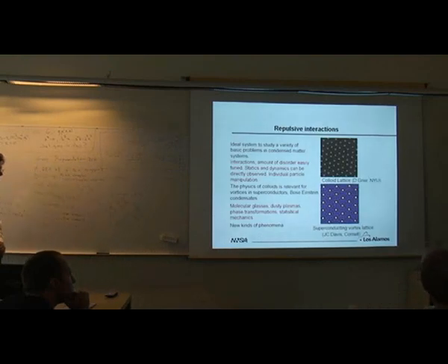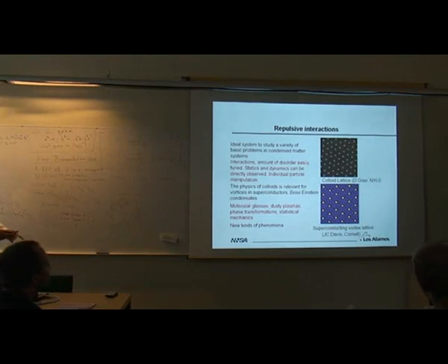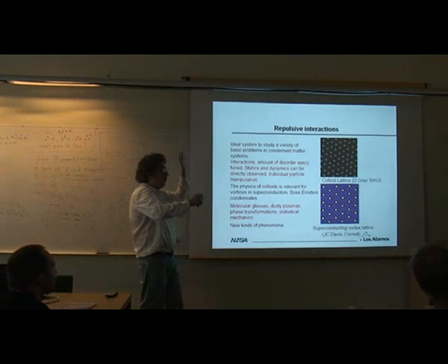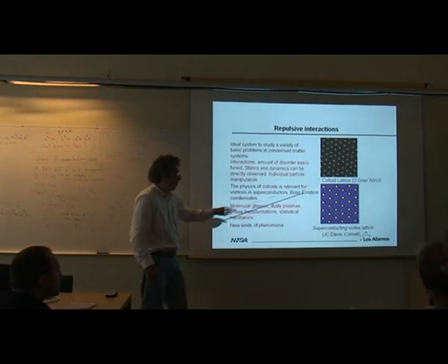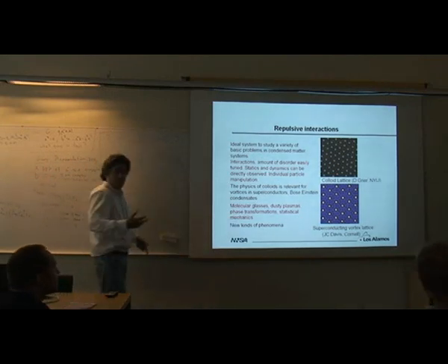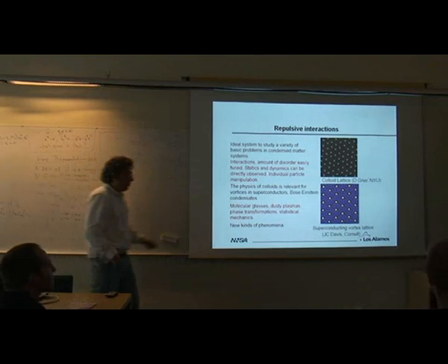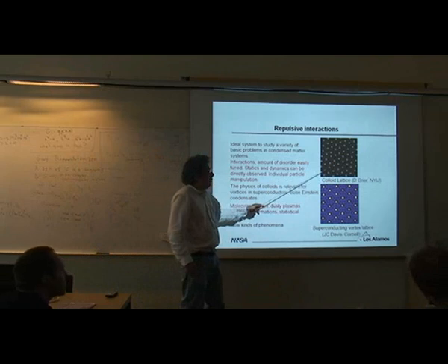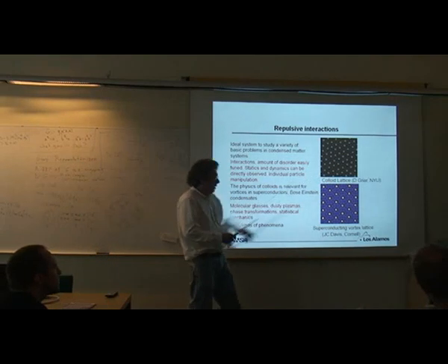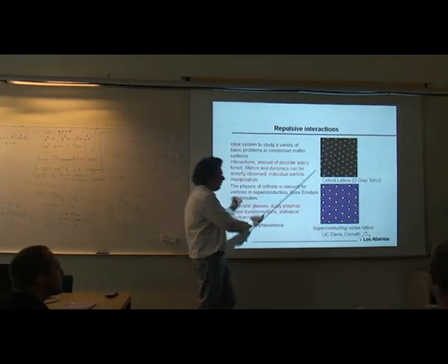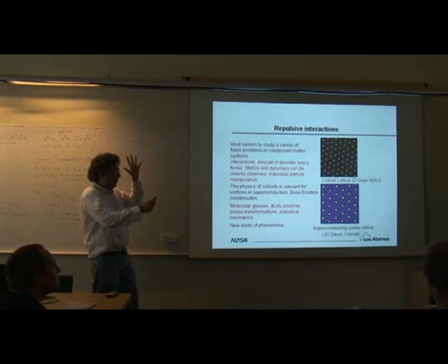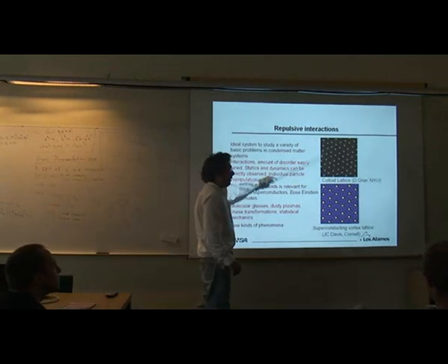Okay, so going closer to the systems that we want to look at in this matter, suppose we have systems with repulsive interactions. I'll emphasize some of the smooth repulsive interactions. So this is a colloidal lattice, which is basically a macro version of a Wigner crystal. These are solid particles in water, essentially, but they have a charge on them. But because they're in solution, there's some screening, so they essentially interact via Yukawa interaction. And that forms this nice triangular lattice.